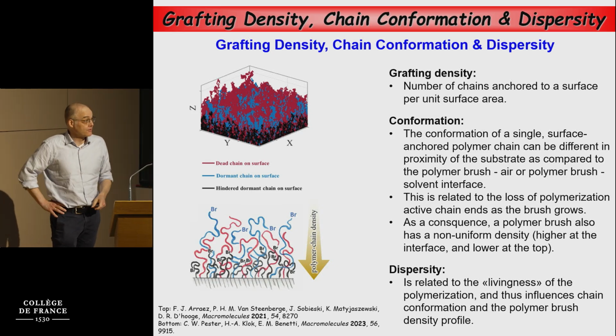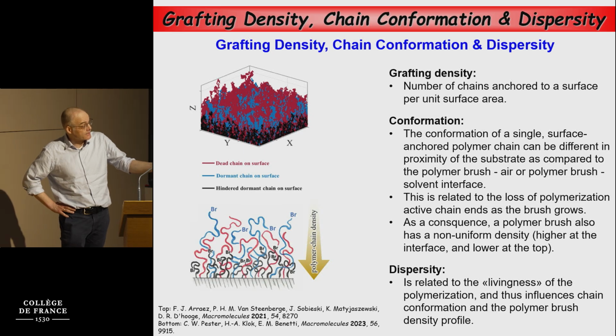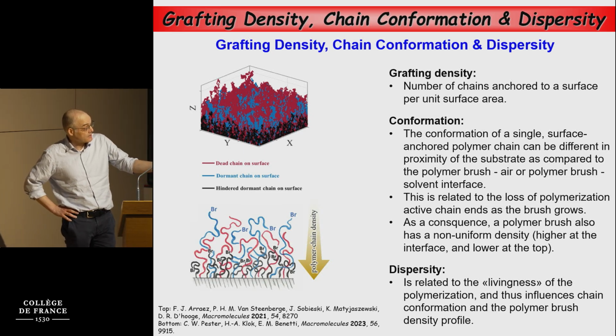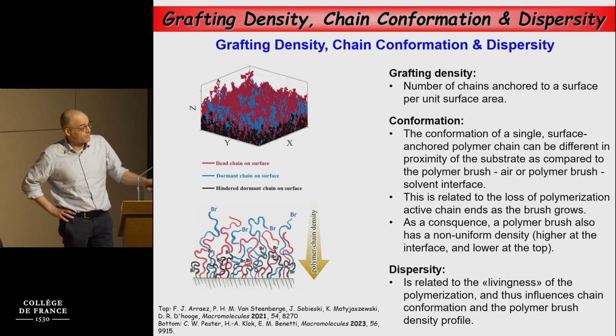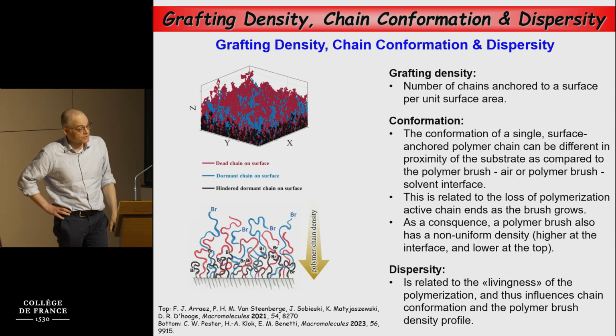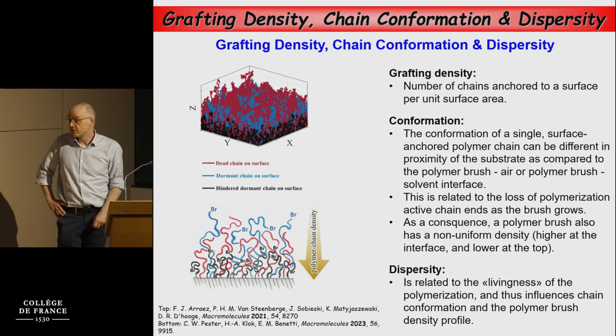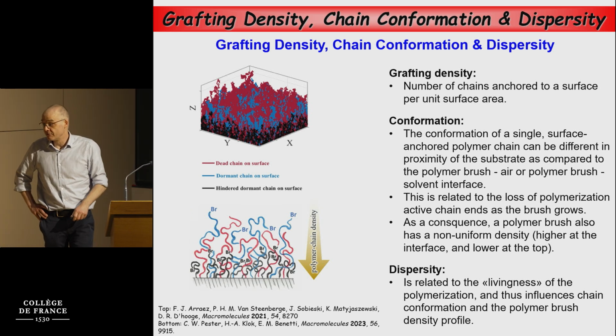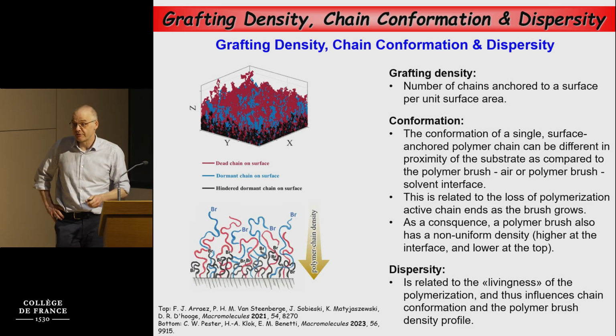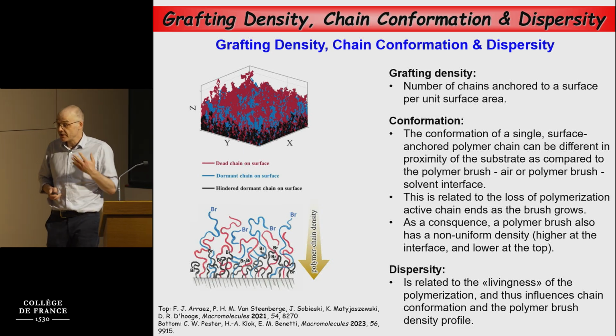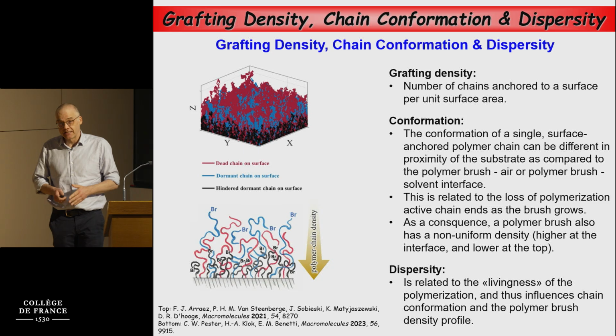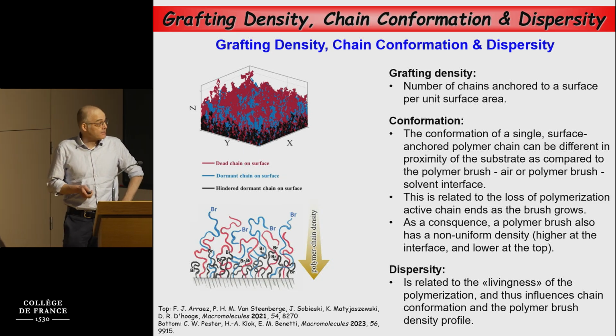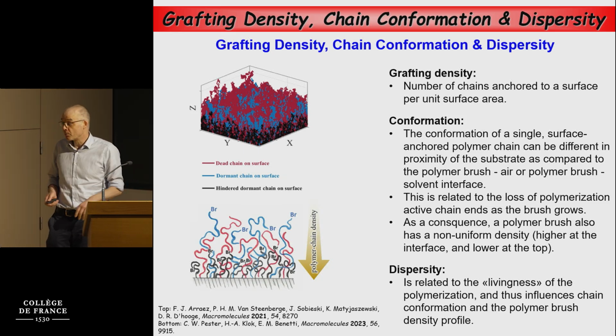And as a consequence of this non-linear gradient in polymer density, there is also a non-linear change in conformation of polymer chains. Chains close to the surface are much more stretched as compared to those further away from the surface. And the more you look at these brush systems and the more properties you try to investigate, the more complex things turn out to be. The research I would like to share with you today is an example that illustrates how complex these systems are.